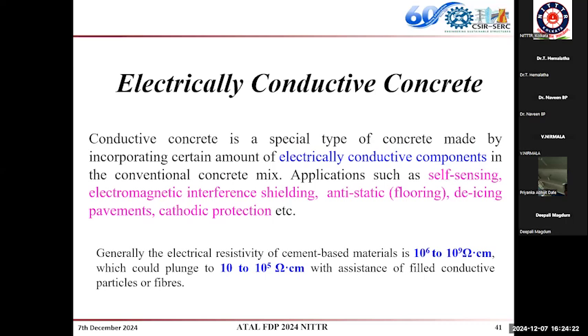Generally, concrete is not conductive in nature. It generally has a resistivity of 10 to the power 6 to 10 to the power 9 ohm centimeter. By incorporating some conductive materials, we can impart electrical conductivity to the concrete and bring down the resistivity to 10 to the power 5 ohm centimeter. When we get that kind of resistivity, then we call it electrically conductive concrete.